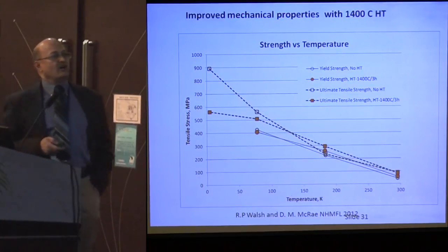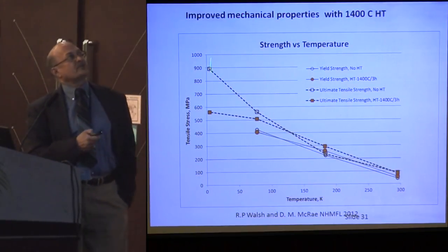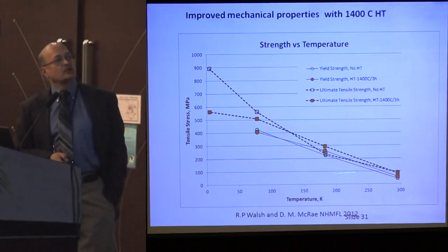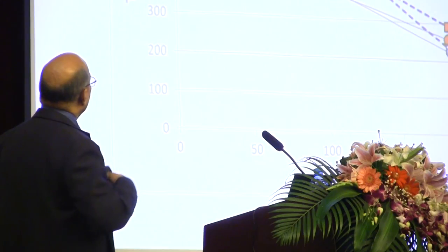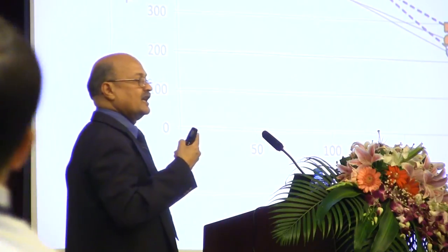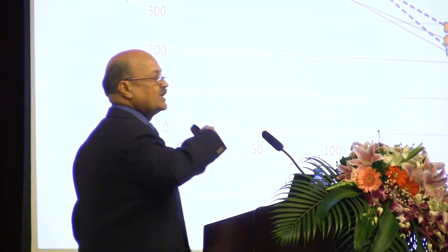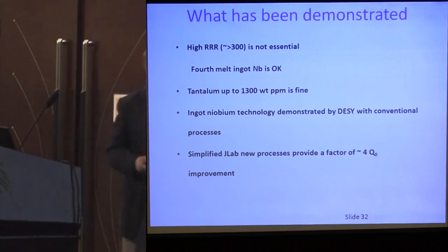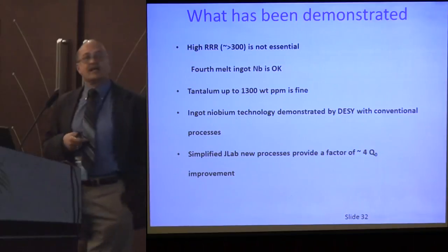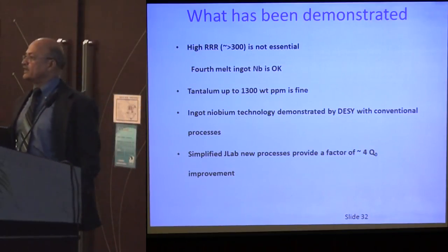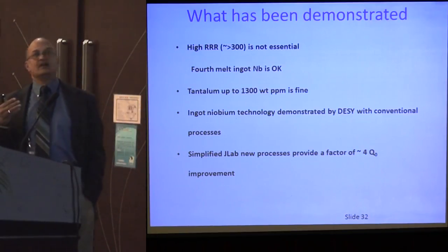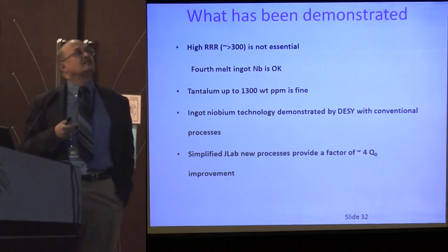We also found that the mechanical properties of ingot niobium improve with these high temperature treatments, which is not the case with fine grain. They degrade with heat treatment because of micro yielding due to the growth of the grains. So what we have done so far is demonstrate that high-RRR niobium is not required for these accelerator structures, which will cut down the cost.